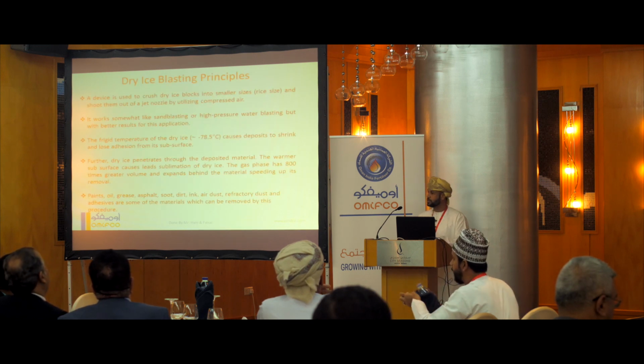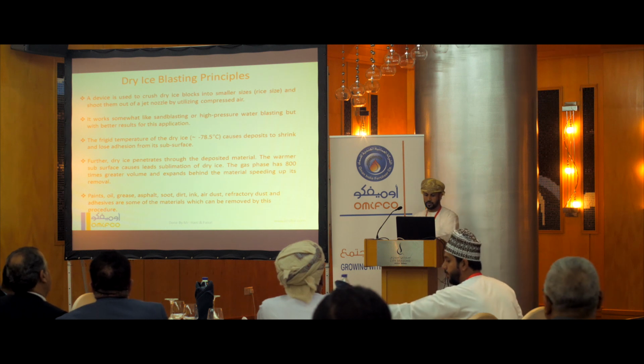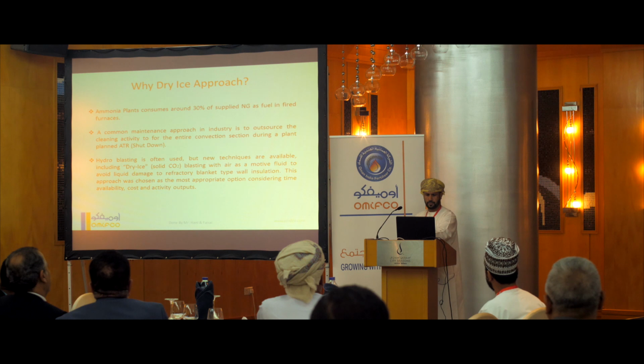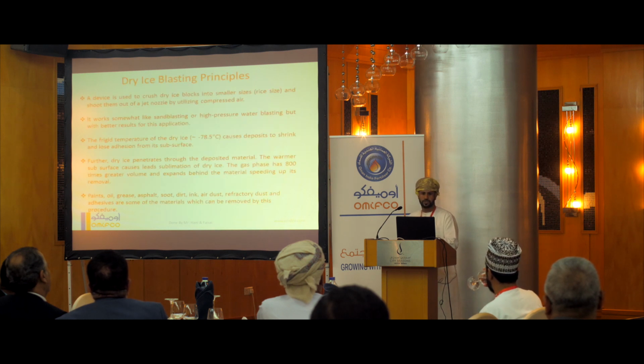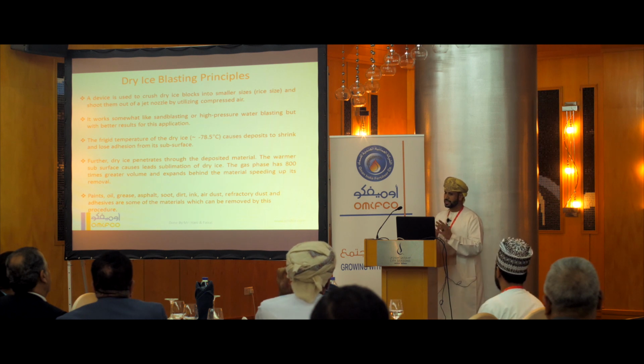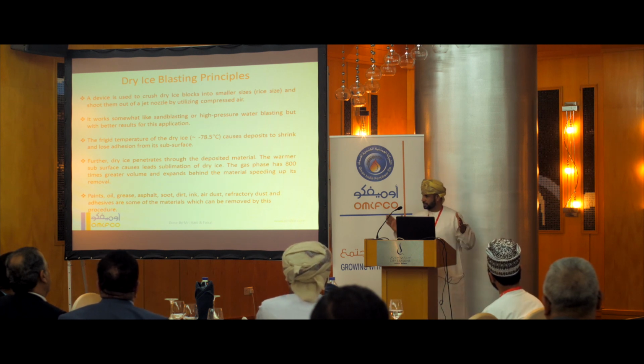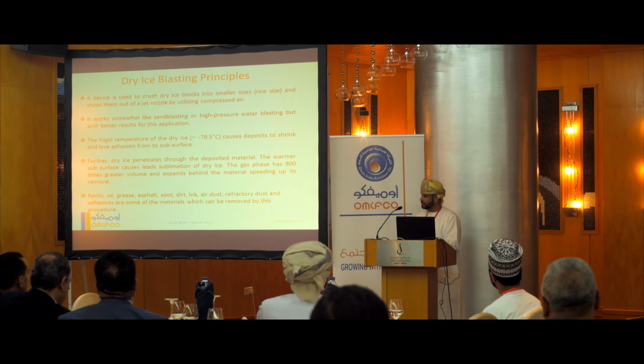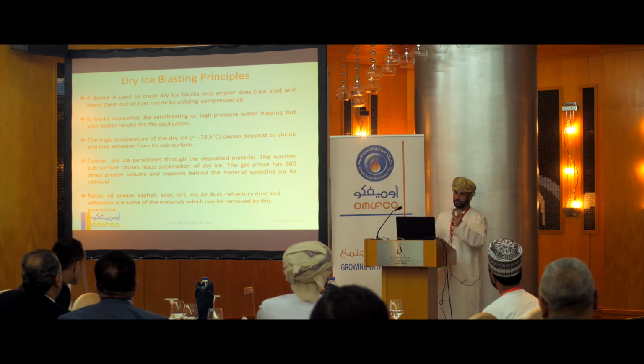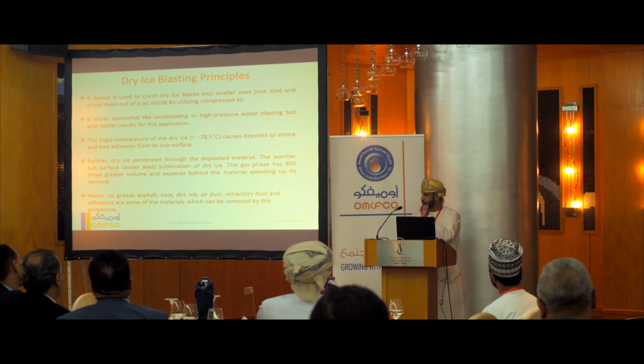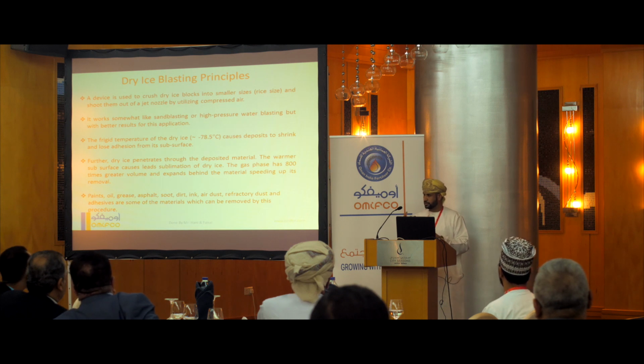The principle of dry ice: we use a device to crush the ice pellets into small pieces, which are propelled by compressed air using a gun. This small size of ice goes with the air and hits the coil itself, and makes the deposit detach from the surface. It is around minus 78 degrees centigrade.